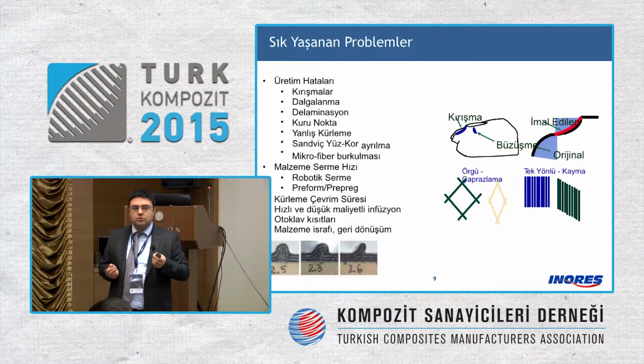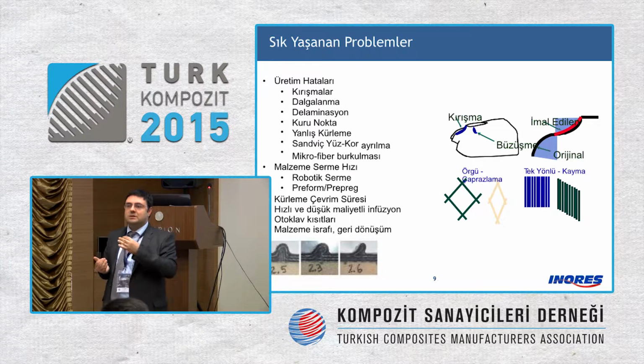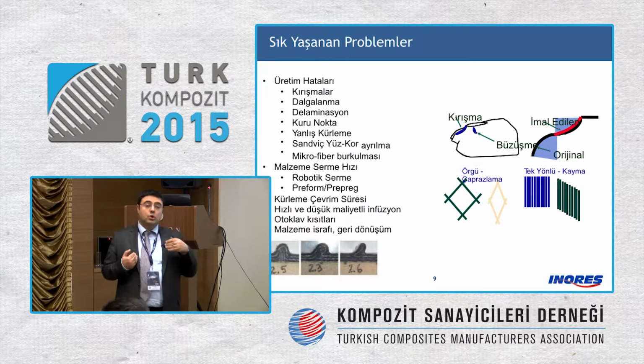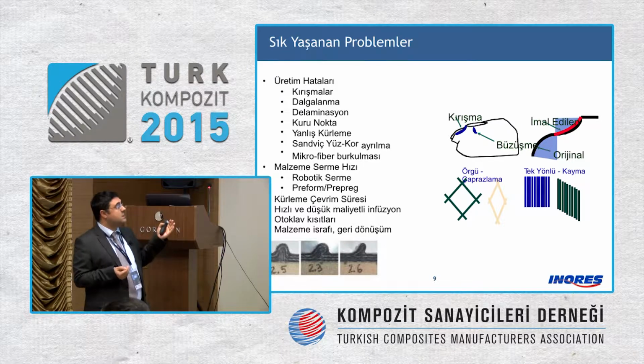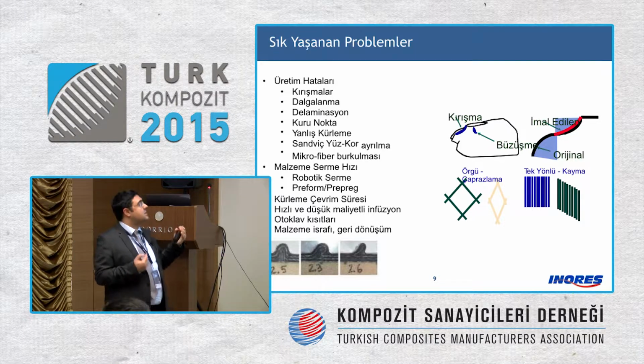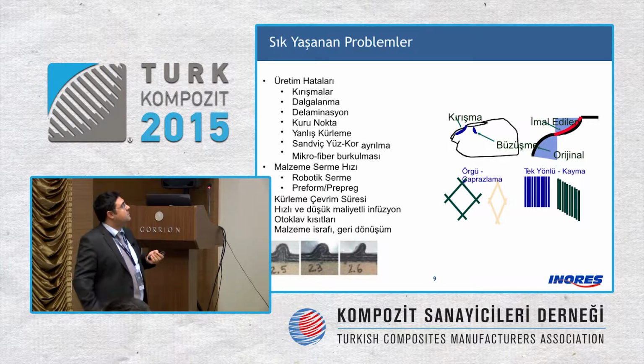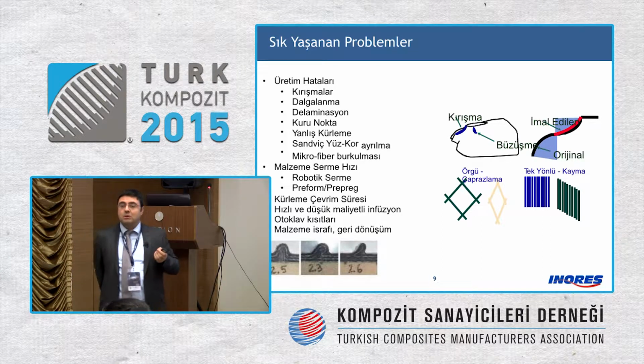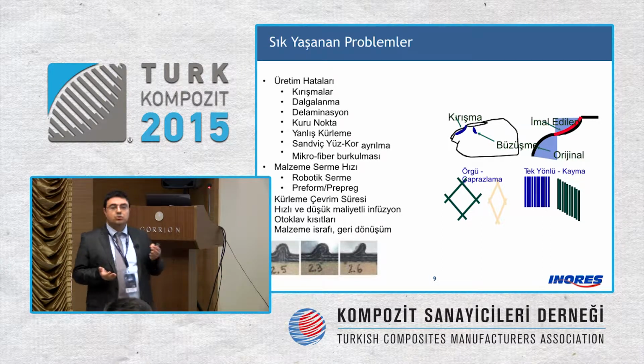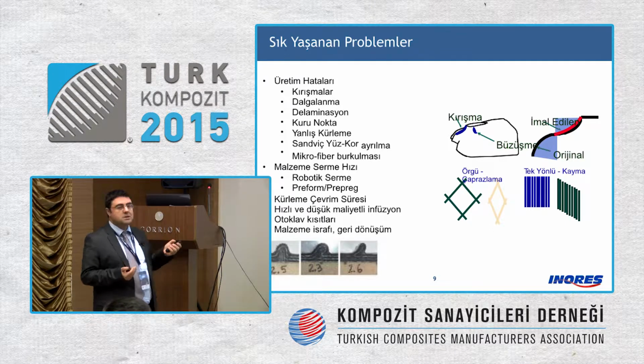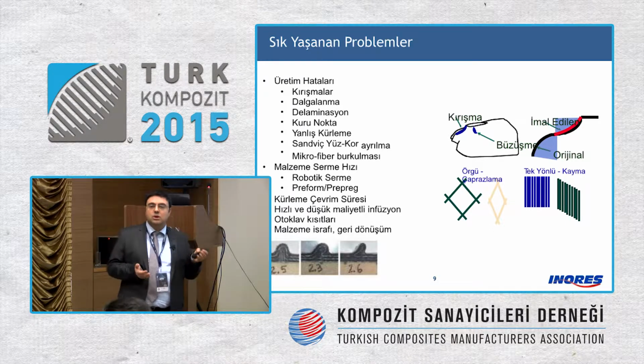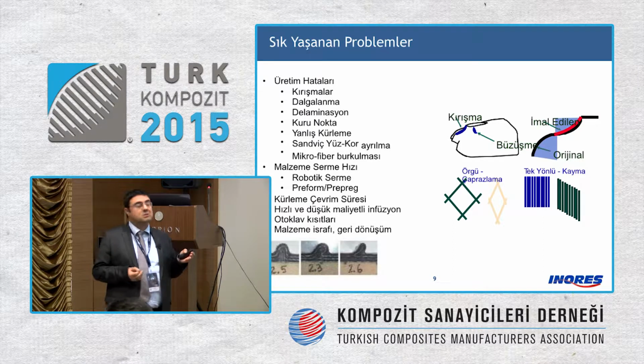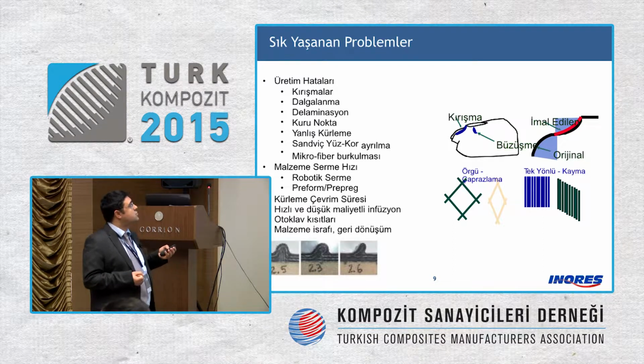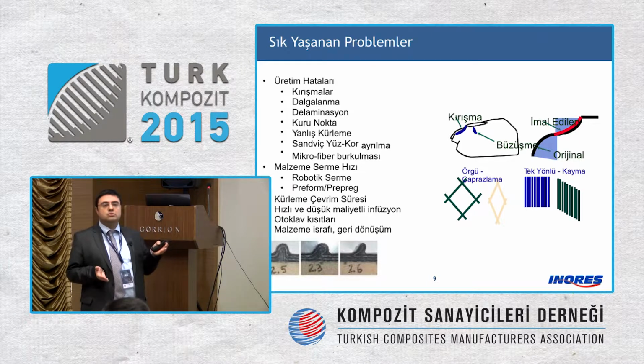Curing process: in the automotive sector, there is a high volume of production. A steel plate is produced in a few seconds, maybe. They want the same speed for composites as well. Therefore, we are working on fast curing resins. It's less than 5 minutes now, but of course, it's not as fast as steel. In the times to follow, there will be lots of developments because there is a high amount of investment.